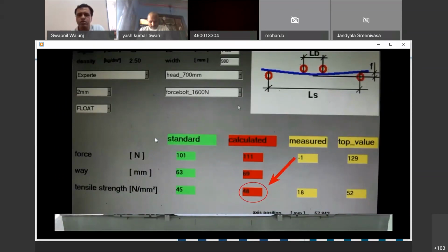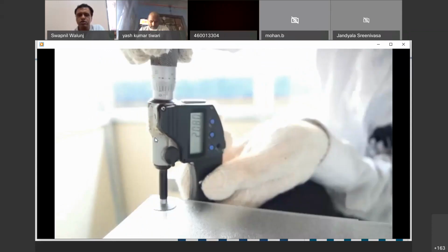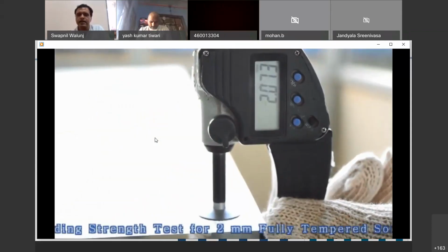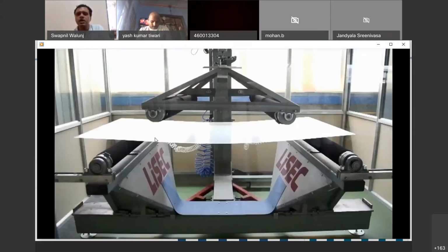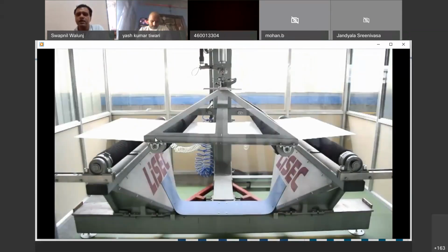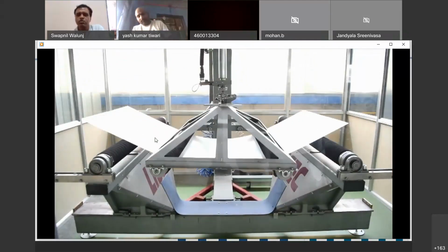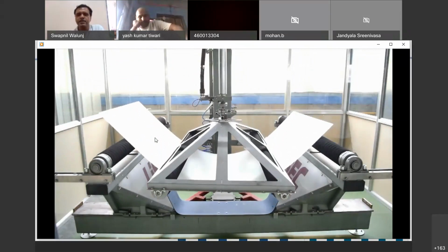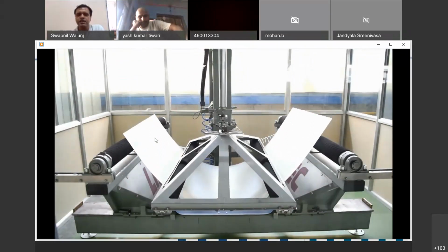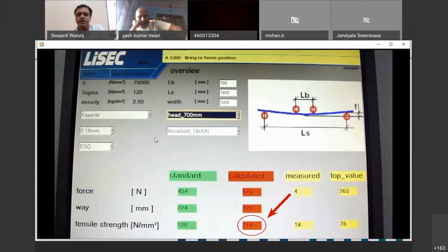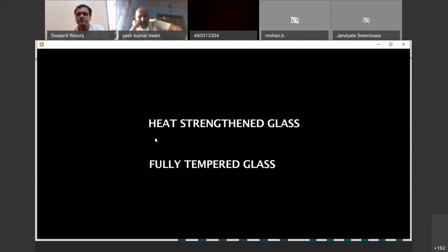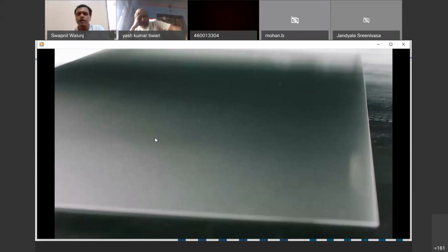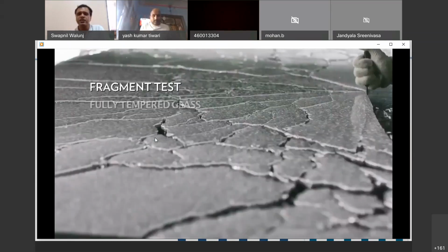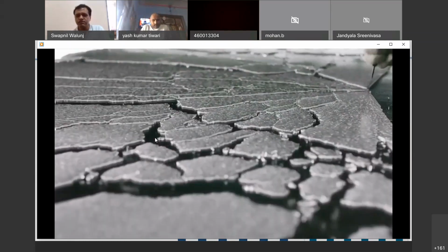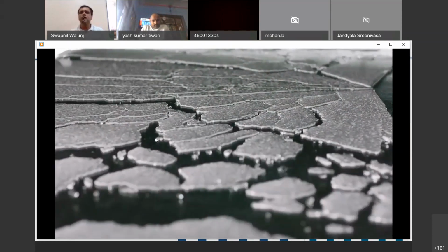So now I'll put a fully tempered 2 mm thick glass on this 4-point bending machine, and we'll subject it to the mechanical strength force. So this is again put on the 4-point bending machine, and you see the kind of bend that it has been able to sustain. Ultimately, it broke at around 214 Newton per mm square. So it is 4 times stronger as compared to the annealed glass. And when it is subjected to the fragment test, it meets all the requirements, and it is as safe as any other glass. So that's the unique feature that this glass has.